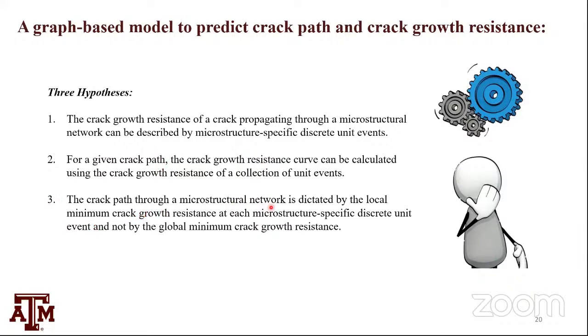The crack path through a microstructure network is dictated by the local minimum crack growth resistance at each microstructure-specific discrete unit event, and not by the global minimum crack growth resistance. Once I tell you, and once we talk about it for 30 seconds, it becomes obvious. It's not something we are pulling out of the air. The crack doesn't know where the target B is, the crack knows A, but the crack knows what is immediately ahead. So the only difference is that A and B are really close apart. They're the distance to the next possible microstructure-specific event. I still need to find out what the local minimization would be, which we don't know yet.